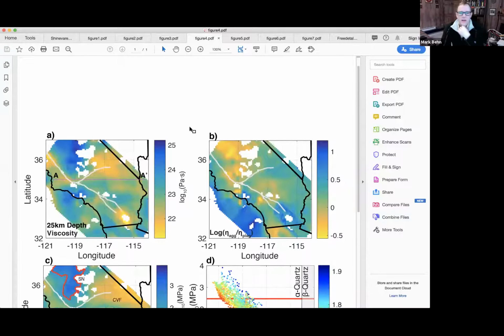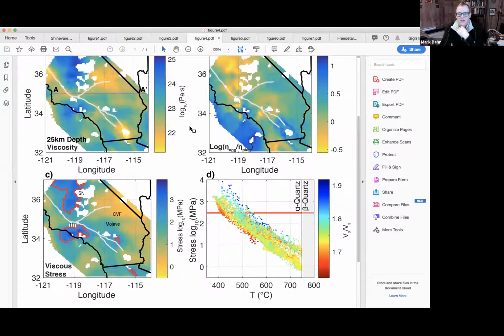And that's what's shown here. So this is essentially a map of viscosity, here normalized to plagioclase viscosity at that same depth. And here again is a plot, in this case, of the stress that comes out of that viscous flow law as a function of temperature.